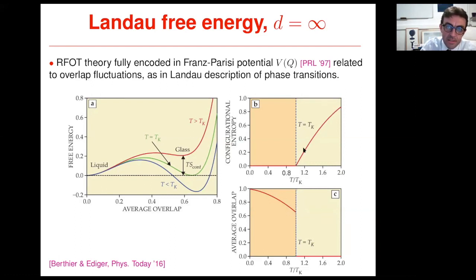So this configurational entropy is going to vanish continuously as we approach this temperature Tk. At the same time, the stable phase is the liquid with the small overlap. And at the glass transition, the overlap is going to jump discontinuously to this new minimum. And so the overlap is going to jump and increase discontinuously across Tk. So this is the mean field picture of the glass transition. Okay, and indeed what I hope you see is that the configurational entropy in this mean field approach, which is valid, as I said, for liquids in large dimensions, realizes exactly the scenario imagined by Kauzmann 70 years ago.